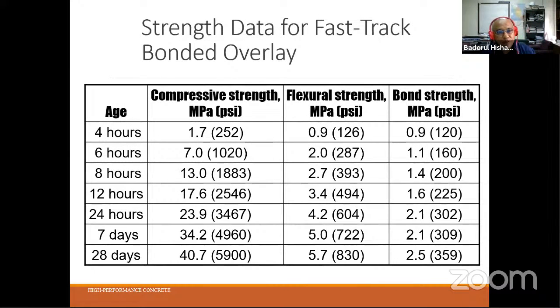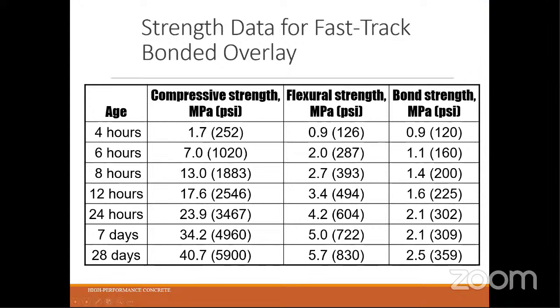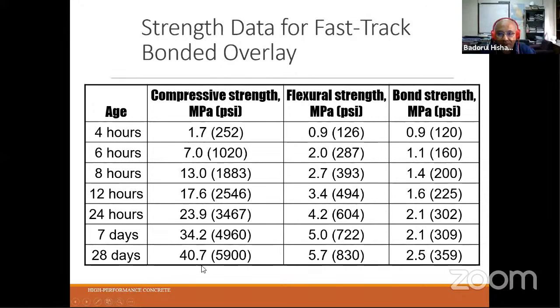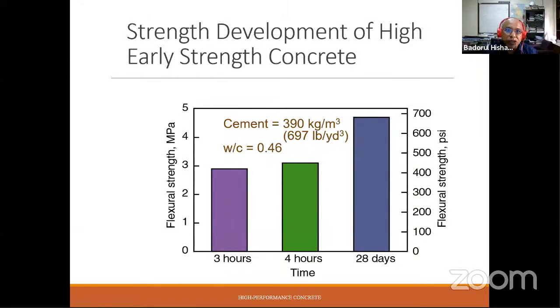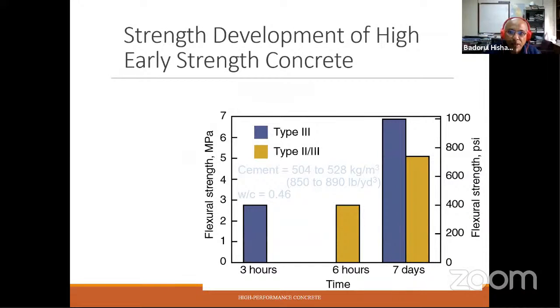Right. Strength data from the fast track, you can see the increase of the strength from hours to 28 days. Here it is only to 40.7, but it can increase more, up to 90 days for the high performance concrete as well. So the strength development of high early strength concretes, you can see the flexural strength and also the times in hours, with 390, which is quite a low amount of cement, and with the very high amount of cement. So there is a difference of the early strength of concrete in the flexural strength